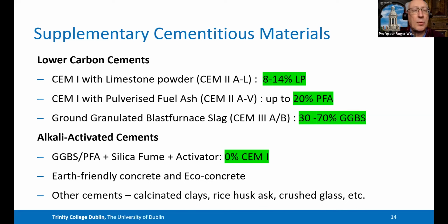Now, there are alternatives which have been used successfully in some countries and are being trialed. And that's where you don't use any Portland cement at all, such as an alkali activated cement. So you have to artificially activate the cement because the lime is no longer available, because you're not hydrating any Portland cement. So you have to artificially activate it to get it to harden and to strengthen at a reasonable pace. And there are other terms we need to be a little bit careful of. Certainly the term earth-friendly concrete uses no Portland cement, but it doesn't insist on using recycled aggregate. And I think that's something that should be looked at. And eco-concretes also suggest that many other types of waste could be put into concrete.